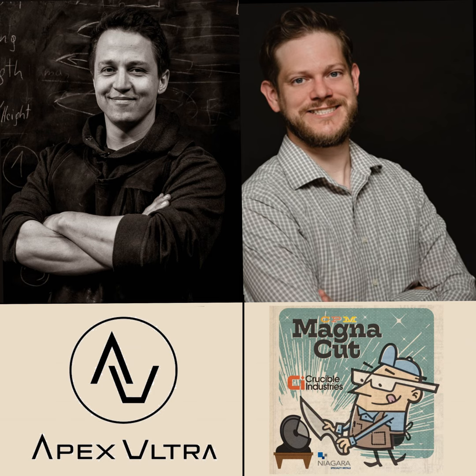Tobias's quench plates are in his press. 30 tons pressure. Really? That'll keep it straight. I also have some in a vise, and it's enough, but you do see a slight difference. I have some in the vise because it makes it easier for students, and I teach a lot of bladesmithing classes to do it themselves. But when I do batches, I put them in the press.